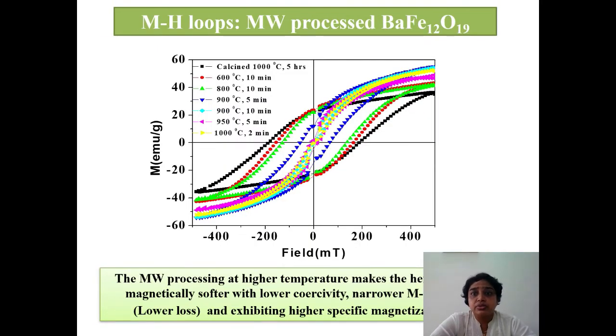Then we measured its magnetic property, and what we found is that the microwave processing at higher temperature has resulted in very soft ferrites, having a coercive field of 2 millitesla. This you can see, this yellow one. The coercive field is very low, that is, they are softer ones, 2 millitesla, and having very high specific magnetization. If you look, that is 52 emu per gram. So this was a tremendous change in the sample just in 2 minutes at 1000 degrees centigrade.